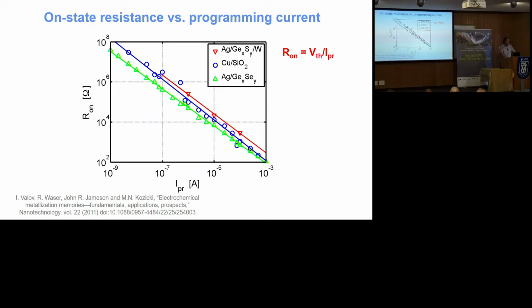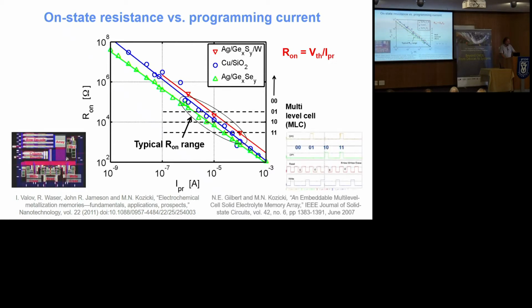It looks something like this, just showing you for a variety of materials. It holds for just about all the materials we use in these devices, with a typical on range in the order of a few kilohms to a few tens of kiloohms as our normal operating range. And over these ranges, we can split it up into multiple resistance levels that can be used to represent different logic states, from the off state as 0,0 through various intermediate states to the lowest resistance state to represent 1,1. And we've succeeded in demonstrating that, as have various other folks, in actual integrated circuits that use